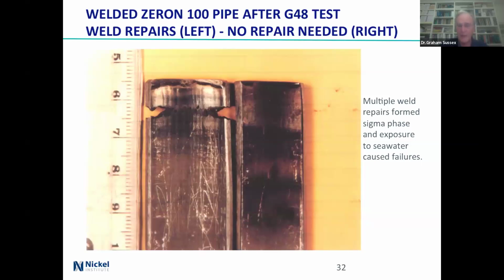The one on the right was after they had done proper welding, as in low heat input. It's gone through the same G48 test, but there's no sensitization. So across that band at that distance, you've got intermetallic phases forming, and it just corrodes quite rapidly. And it was sigma phase. I've seen tests where you put 20% or so of sigma in there and then heat treat it, it goes away and it's beautiful. But of course, people don't do that if they're building stuff on the site.